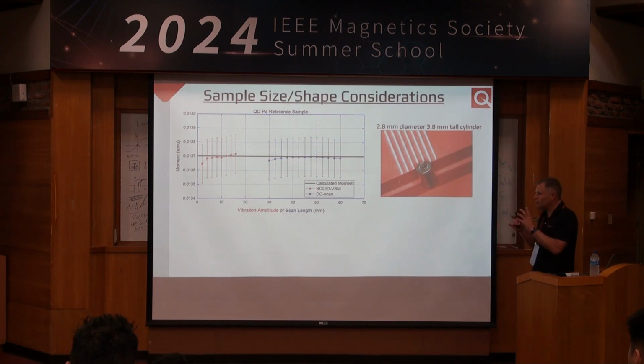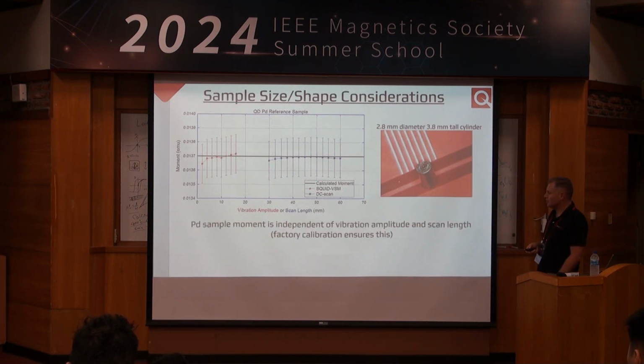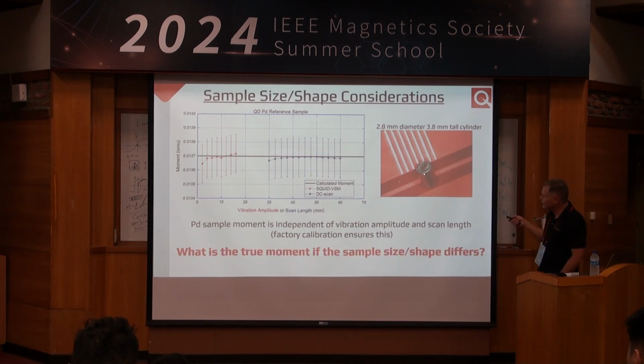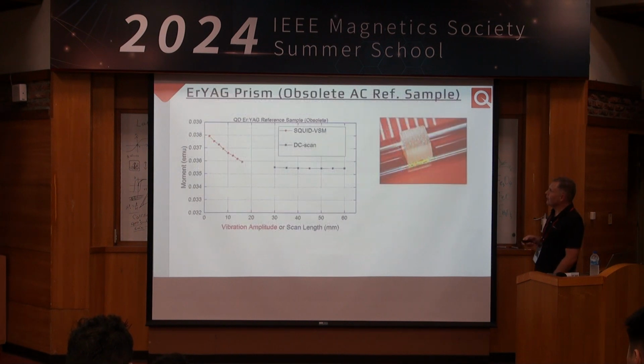There are additional calibration things to ensure that this is the case if you have a sample that looks like this. But what is the true moment if the sample size and shape is different than this? So I'll show you what that looks like here. This here is a sample. It's a piece of erbium YAG. This is an obsolete AC reference sample that we used to use. But clearly it's not a cylinder.